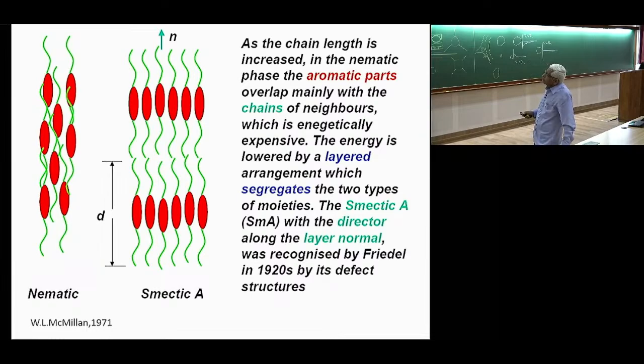But then you lose the dispersion energy, because that depends quadratically on the anisotropy of the polarizability. So this dispersion interaction depends upon the square of the polarizability anisotropy, which is a negative term, that will be prevalent only if these two are close. So if the chain is very short, then the entropy wins over and you get the nematic phase.